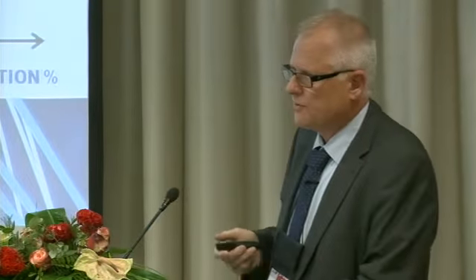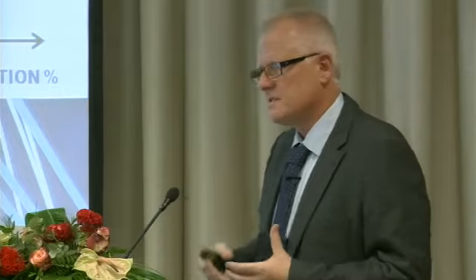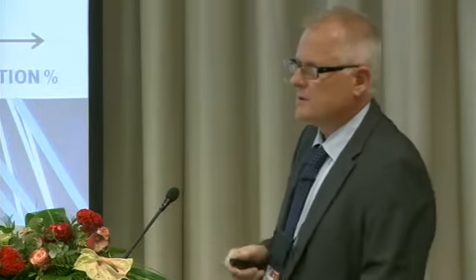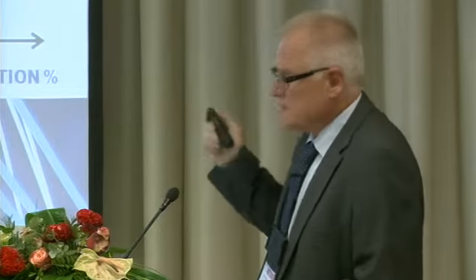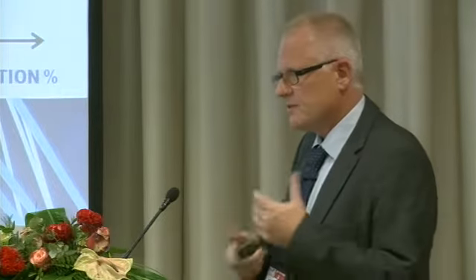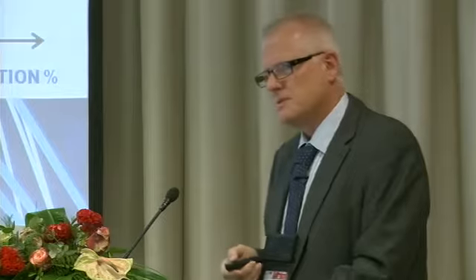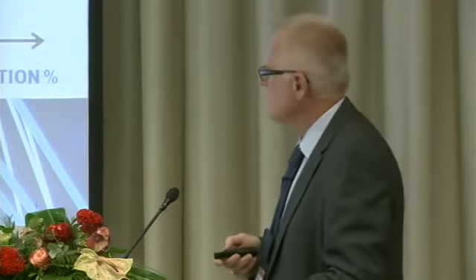Simulation, yeah. I don't know how the simulation program looks for cold forming, but I think when we start the simulation for the hot forming, we have elongation curves. Depending on how high this part is, we have a lot of elongation, but we call them heating curves because these follow the process down from 920 to when we have closed the dies and we are quenching out the heat and we open it up again, because we need to calculate for shrinking so we can do compensations. So we actually design the die bigger than the part when it has cooled down. So in the simulation program we have different heatings, and we have cooling water inside when we do the simulation, so we can be as correct as possible when we make the simulations.